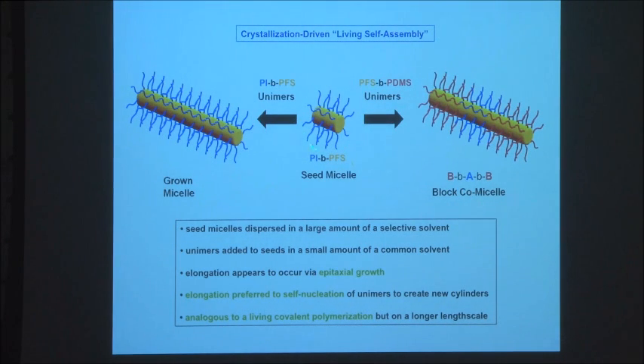So if you take one of these cylinders with a crystalline PFS core, and to illustrate this, we usually take a small cylinder, a short cylinder, which we make by sonication. I'll explain how we do this in a moment. If you take these structures, these we regard as seed structures. If you then add more unimer to them, for example, here we have PFS polyisoprene, the PFS blocks in the unimers you add will deposit, orient, and crystallize on the ends of the pre-existing seed micelle, and the structures will grow.